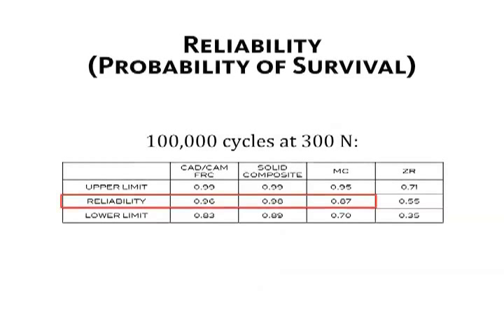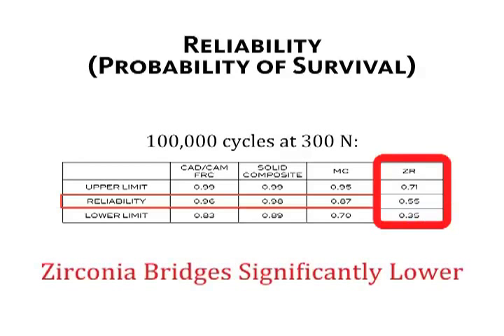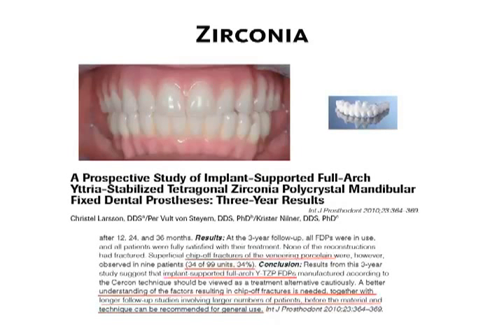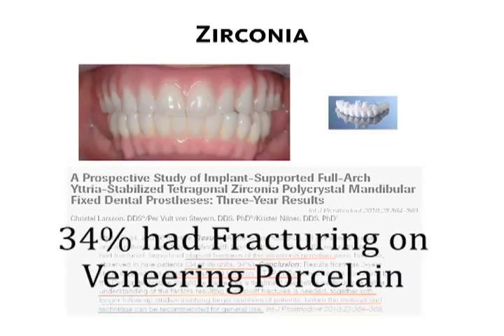When the probabilities of survival, here given as percentage values, are compared, these three groups, comprised of the fiber reinforced composite framework, the solid composite, and the metal ceramic, were not statistically different from each other, whereas the zirconia bridges were significantly lower. As we move on to even more complex scenarios, such as full arch zirconia reconstructions, it is important to bear in mind that chipping scenarios are also a concern and have been shown to be somewhat frequent, as in this study that showed 34% of fracture within the veneering porcelain in a 3-year follow-up clinical study.